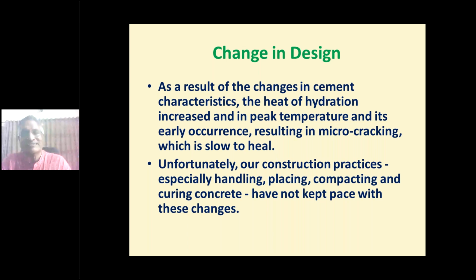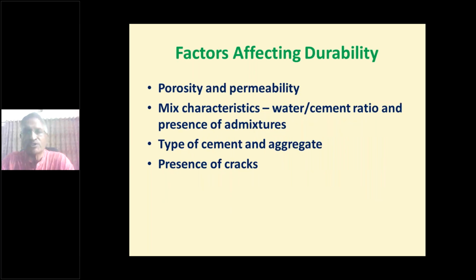The heat of hydration and peak temperature are increased, and because it occurs very early, microcracking starts, and naturally that leads to deterioration. It is a very slow process to heal. Unfortunately, our construction practices, especially in handling, placing, compacting, and curing, have not kept pace with these changes. So it is extremely necessary to create a bridge between the development in cement production and the practices in the field. We should create communication between the two and create processes and procedures, SOPs, to do this.